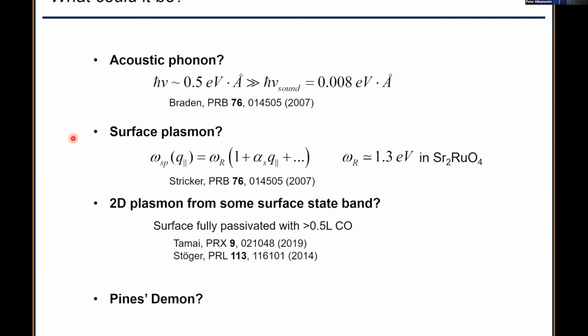So if you look at surface plasmons in techniques like EELS, they all show up at what is called the Ritchie frequency, which in a simple Drude metal is omega p divided by the square root of 2, though what it really is is the point where the real part of the dielectric function crosses -1.